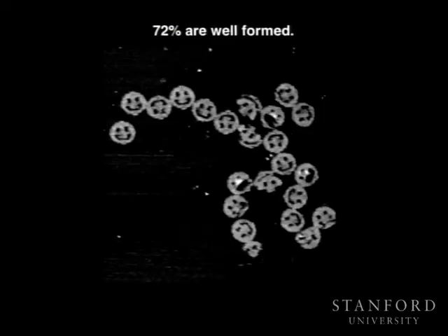And so then we take an atomic force micrograph, and you'll see immediately the difference between the design smiley faces, and some of these guys have their noses punched out and their jaws flipped over their head and stuff like that. So there's a question of why is that, right? That's a component of the yield. So only 72% of these guys look like the design, and you have to figure out how you measure this, right? What do you mean by they look like the smiley face? They don't have holes that are too big, for example, above a certain size. But these guys are not all well formed, and I'll get back to some of the reasons why that might be the case for these particular guys.